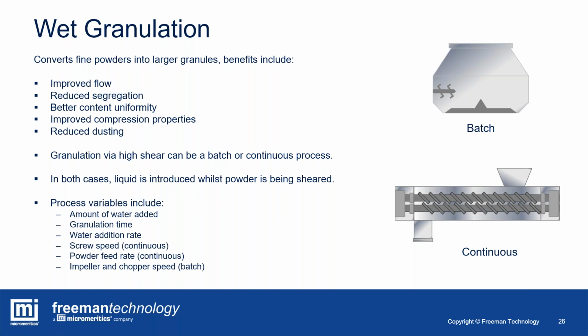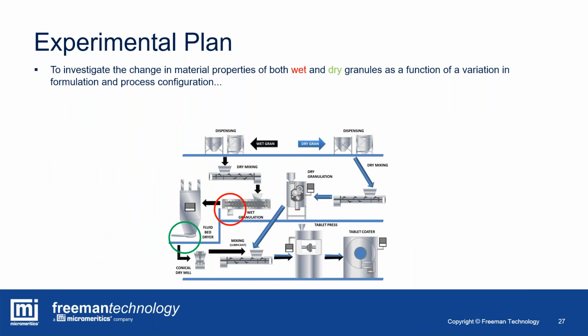And your variables are process specific, but of course the amount of water you add is something you can control and is important. The granulation time, duration of granulation within batch processes, the rate at which water is added, the screw speed for the continuous setup, the powder feed rate into that screw, and for batch, the impeller and the chopper speed. And so what we did in this experimental program, which was in fact a collaboration with GEA Pharma Systems, was to investigate the change in material properties, both of the wet and the dry granules as intermediates, as a function of changes in the formulation and also the process configuration.